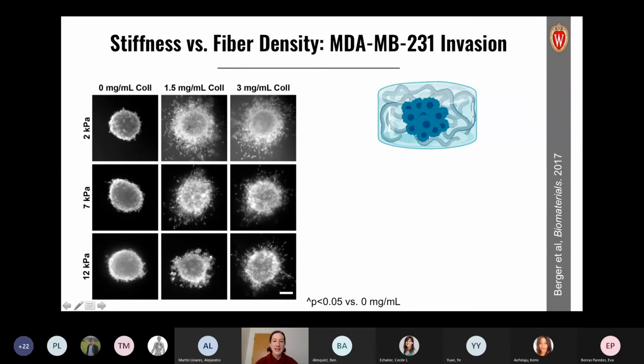But basically, it has a collagen-based backbone. And what we've done here, though, is we've used collagen in a couple of different forms. We've used collagen in a gelatin form, so that's denatured, so we can control the stiffness. And we've used collagen in its native form, so we can still have fibers. And we did that because fibers have been shown to be important for the invasion of multiple types of cancer. So we wanted to make sure we had those fibers present. We didn't actually understand how important they would be until we started doing this study, though. We thought they just helped to facilitate certain cellular events. We didn't realize that some cellular events wouldn't even occur without the fibers. But in fact, that's what happened.